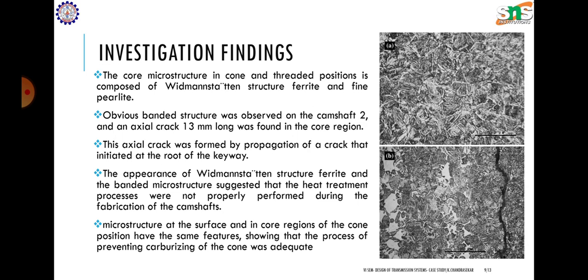The appearance of Widmanstätten structure ferrite and the banded microstructures suggested that the heat treatment process was not properly performed during the fabrication of the camshaft. So this is also a reason: the heat treatment was not done properly.